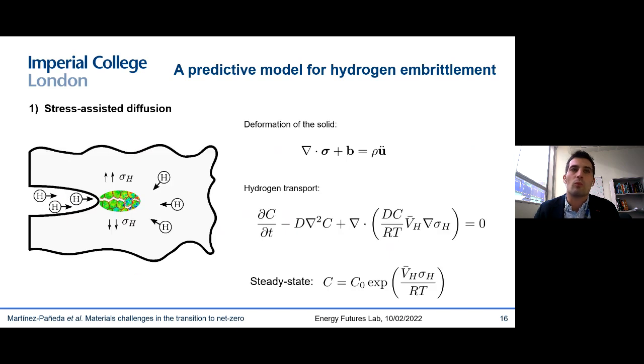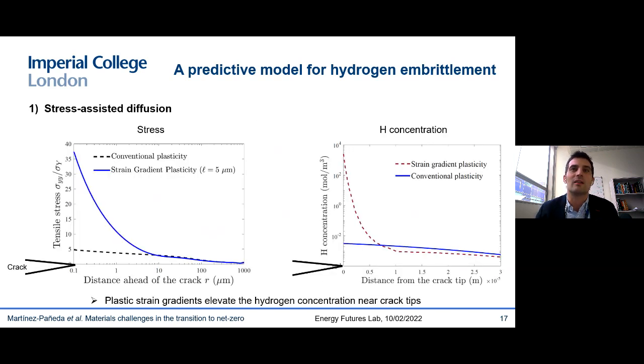And then basically what I want to emphasize is the connection with mechanics, right? It is very strongly coupled. You can see here, this is the steady state solution of this transient problem. And you can see that the hydrogen content depends on this exponential term that includes the hydrostatic stress. So if we want to know how much hydrogen we have, which is key to determine when cracks will initiate and grow, we also need to know exactly what the stresses are. And the key point here, without getting into too many details, is that the critical distance ahead of a crack where hydrogen-assisted cracking takes place is only a few microns.